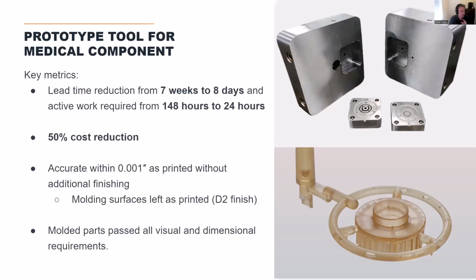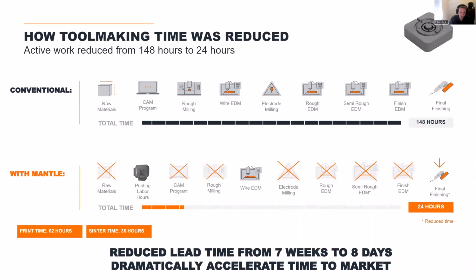The molding surfaces, this is important to know, the molding surfaces here were left as printed. Our tools kind of generally see a D2 surface finish similar to a Sinker EDM process. So for this application, that kind of matte surface finish was totally fine. So they're able to leave that all as printed, and the molded parts passed all visual and dimensional inspections, which was great. They molded a couple hundred parts here, which was awesome.